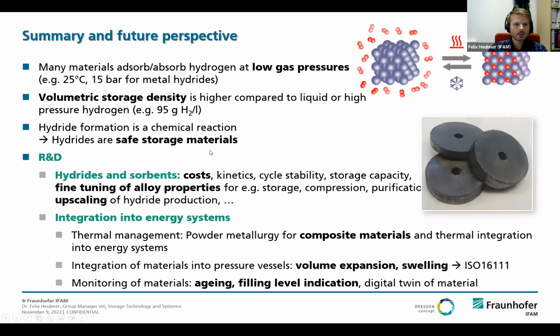To sum up this talk and give maybe some outlook about future perspectives in terms of R&D and materials. A lot of materials absorb or adsorb hydrogen at low gas pressures, but it's very important to understand this chemical reaction. So heat needs to be used for desorption of hydrogen, for example. One of the main benefits is the enormous volumetric storage density. It's up to 95 gram hydrogen per liter for very common alloys that are cycle stable, can be even higher for complex materials, up to 150 gram hydrogen per liter, so factor 3 compared to 700 bar gas storage, for example, on the level of the material.